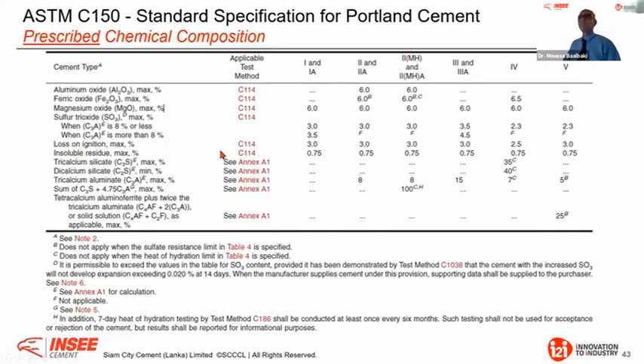Now, LOI, 3%, nothing really special. Insoluble residue, 0.75, we are around 1. After that, C3S, C2S, here you have also limitations, especially for heat, for low heat cement. This is why you need to develop what you call a belitic cement, and nobody will do it today. These are cements where you have more C2S than C3S, and these are very lazy cements at early age. In some countries, you will find them because from the raw material, very often they have a high amount of C2S. They are not as low as 35% in C3S. For example, here, normal C3S will be around above 55, 60%, and they will be below 55. That is for C2S, C3S.